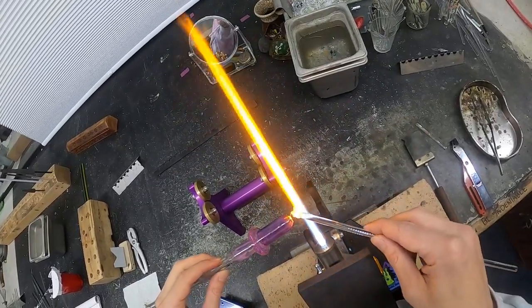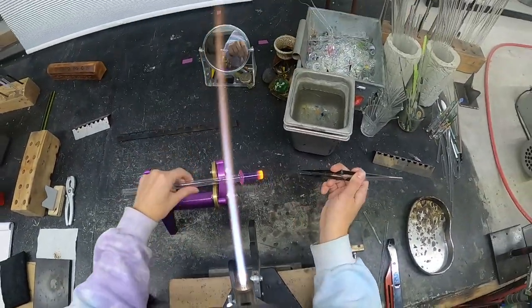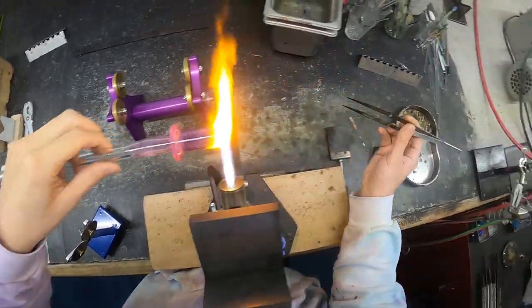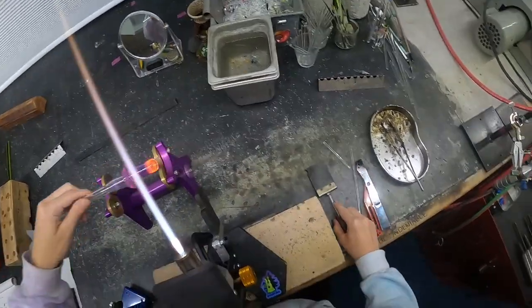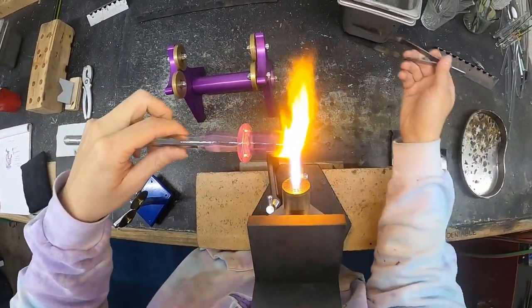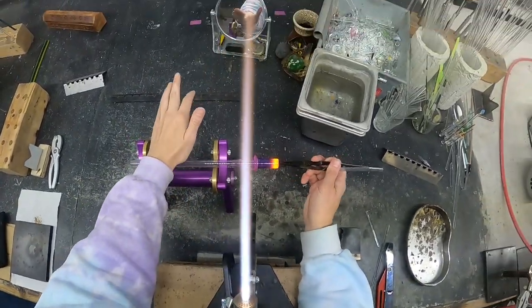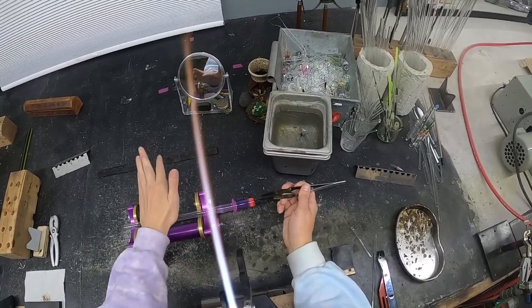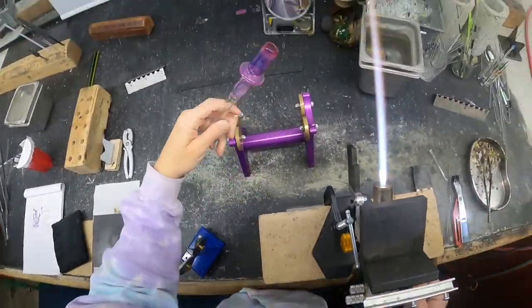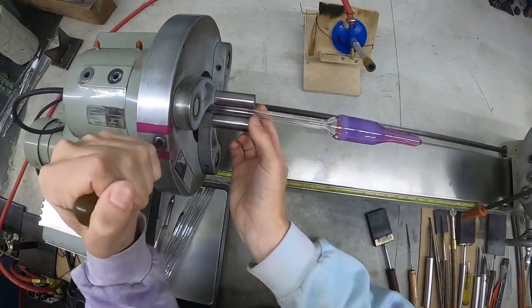This is on the tailstock side so I do have to go right to the bench and even it out. Open that hole and get her prepped. Anytime I let things cool from the kiln, I try to have an open hole. It seems like moisture gets built up inside the piece if you let it air-cool from the kiln. Sometimes it doesn't go away, so I definitely try to avoid that at all costs. Even at the end of the day when I'm done with a big exo, I'll pop a hole in a convenient spot just so it doesn't leave scum inside.